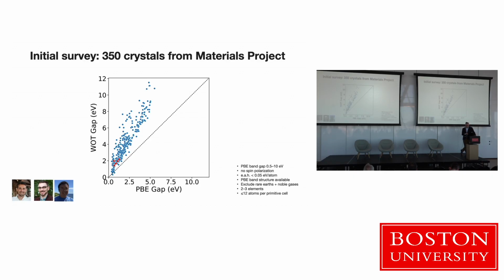So this is the predicted gap on the left axis, and then on the bottom is the PBE gap in the Materials Project. And so you can sort of see the trend that PBE is underestimating the gap. But you can also see that if you pick a value of the PBE gap, there are materials with very different hybrid gaps. So the point there is that you can't just say, let's just multiply each PBE gap by 2. That doesn't work. It's not a simple theory; the correction is not a simple function of the PBE gap.